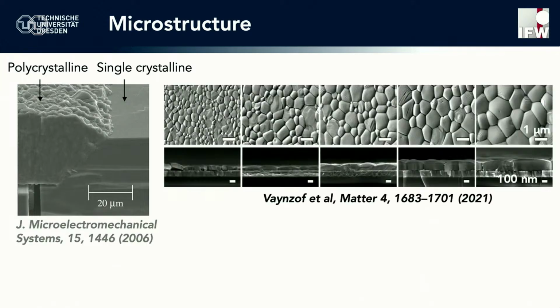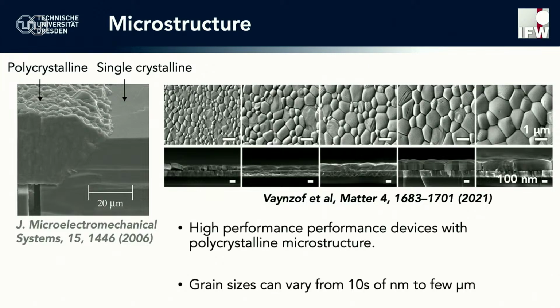Now, how would perovskite look like? We actually examined a number of ways to control their microstructure, but in all cases, you can clearly see this is a polycrystalline material. We can tune the grain size from tens of nanometers, maybe to a few microns, but still many interfaces, many boundaries, and yet they work remarkably well. You can also see here the thickness that I just mentioned to you. So in this case, you can see in the cross sections that the thickness of the perovskite layer would be perhaps a couple of hundreds of nanometers. And that's much, much less than the hundreds of microns we would require for a silicon solar cell.